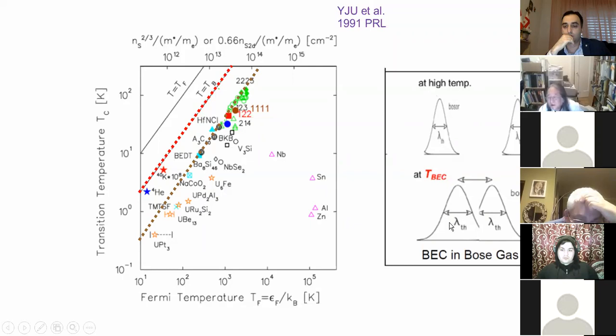And if the particle is a boson, then in a Bose gas, these bosons would have a tendency to make a special coherence of the wave function, and that is called Bose-Einstein condensation. And this Bose-Einstein condensation should have happened here. Okay. So for this hypothetical idealized situation, compared to this hypothetical Bose condensation, the real TC, the transition temperature of these new superconductors, is reduced, and they are reduced by about a factor of 4 or 5.